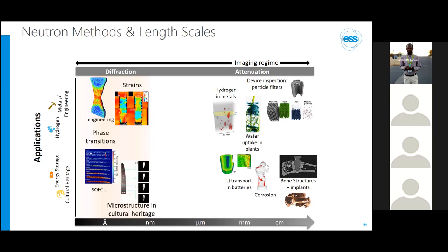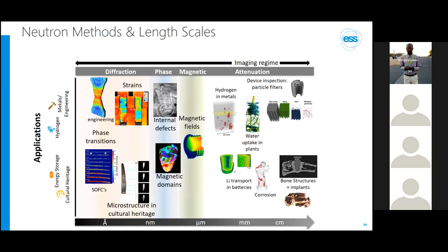solid oxide fuel cells. One can also exploit phase contrast to reveal internal lattice defects in metals or to visualize magnetic domains. This can then be used, for example, to study and optimize electrical steel used in electric motors. And due to the fact that neutrons have a nuclear spin and a magnetic moment, one can also exploit this for imaging of magnetic fields. I will now mostly focus on diffraction contrast in neutron imaging and show you some more detailed examples of that.